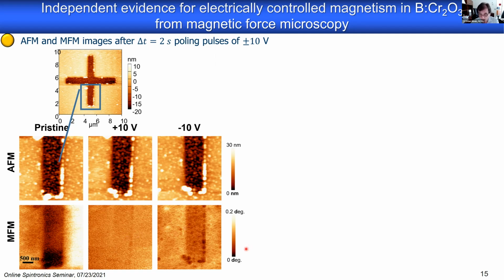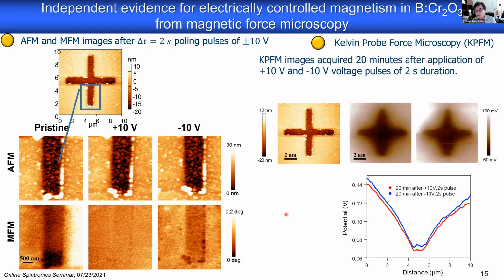But Alexei wanted to be very careful and wanted to make sure there are no other potential artifacts. So he said there could be charging effects. So he measured Kelvin force microscopy in addition. And the Kelvin force microscopy, which basically measures the surface potential when you scan across this leg here, was identical no matter what type of voltage we applied. So we could exclude charging artifacts, and therefore, indeed, this signal is magnetic.